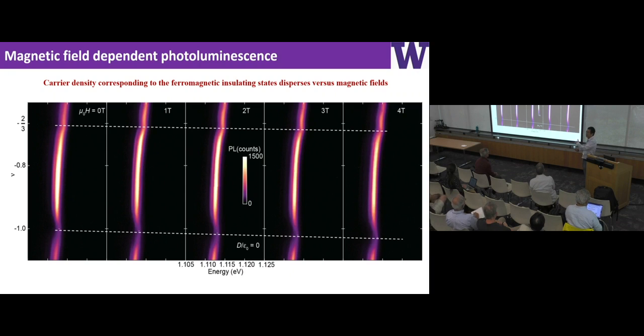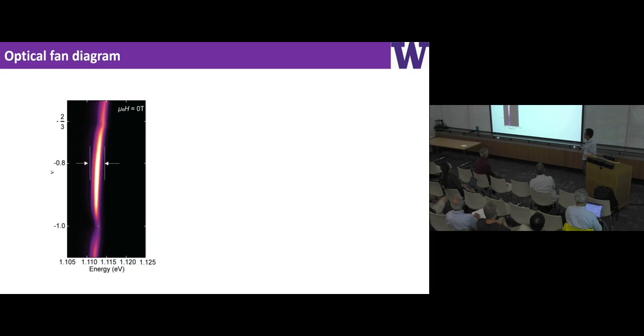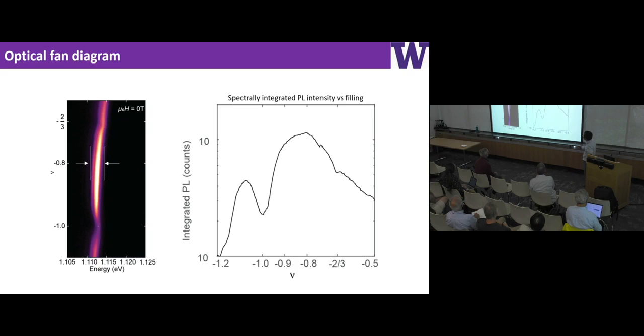Basically, there are dispersions. This tells us there's something actually topological. But this is not very quantitative, right? To do a quantitative comparison, what we do is perform a spectral integration of this luminescence over these spectral windows. Then we plot this spectrally integrated PL as a function of filling factor at a particular magnetic field, for example. Then you will see two dips corresponding to these two gapped states.